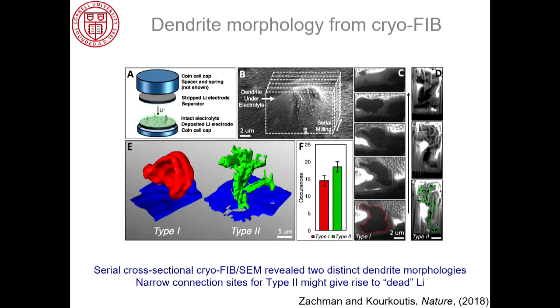So the first one to map over very easily is freeze the material and look at it. So, you know, with batteries, I normally have a problem. I have a liquid electrolyte. I have an SEI layer. And then I have my electrode, which is made out of something, in case it was pure lithium, something that's not going to like to be exposed to air. But hey, if you go from glove box to liquid nitrogen, there's no oxygen around in liquid nitrogen. It all freezes out. And so you can use a focused ion beam system to cut into this solid liquid interface that's been snap frozen quickly enough that nothing crystallized.